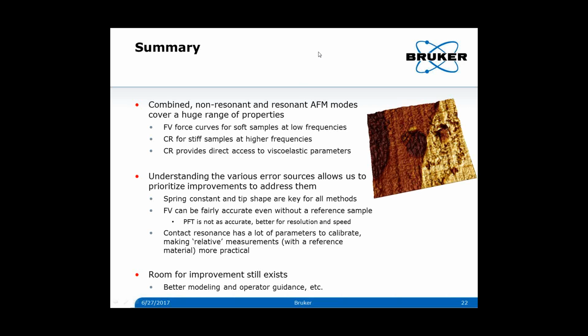It says, are there any limits on sample modulus that contact resonance cannot measure? Yeah, so that's obviously a good question. On the upper limit, not really. Contact resonance was actually designed initially to try and probe stiff samples. So, you know, metals, hundreds of gigapascals are not an issue. The limitations really fall on the lower end. And in my experience, I'm comfortable using contact resonance for materials that are down to a gigapascal, so 1 gigapascal. Lower, there are problems with the models. Samples that have a lot of adhesion, where the models don't really integrate that, also will suffer. But I would say 1 gigapascal is the lower limit, and upper limit, hundreds of gigapascals is fine.